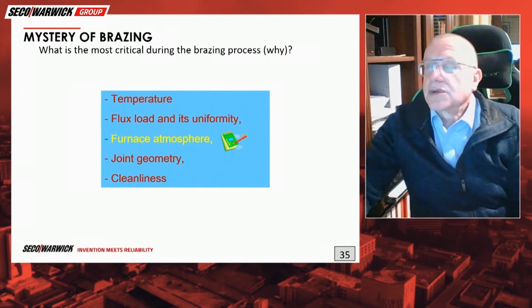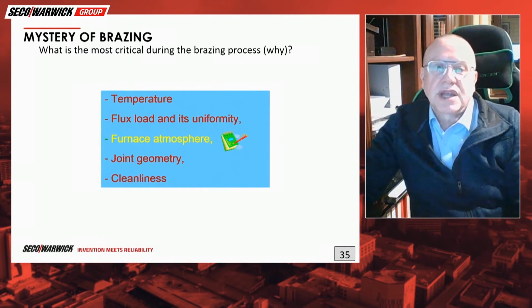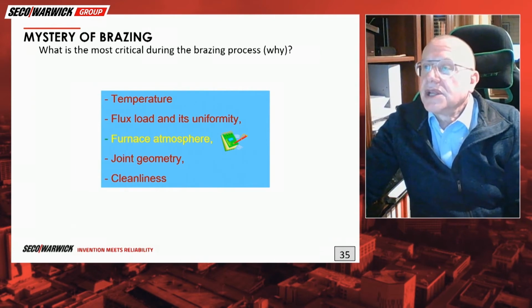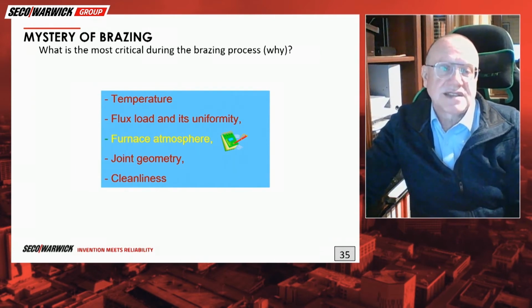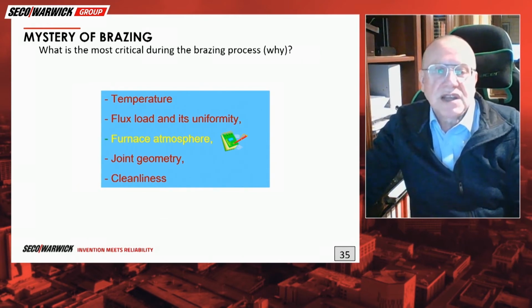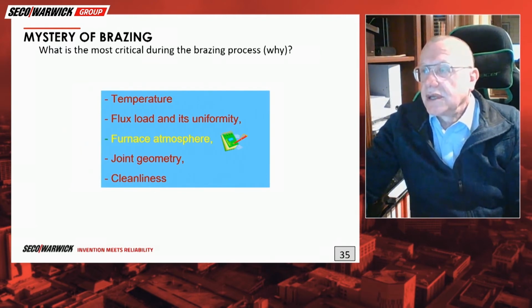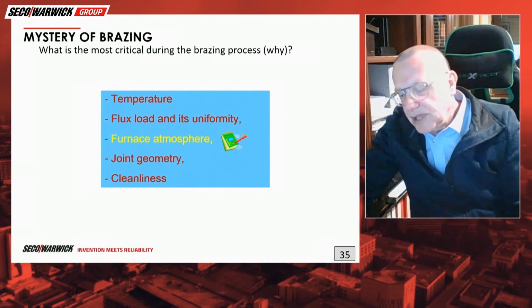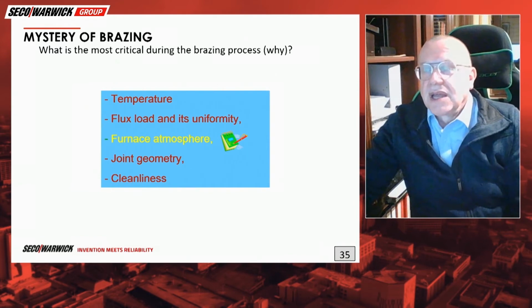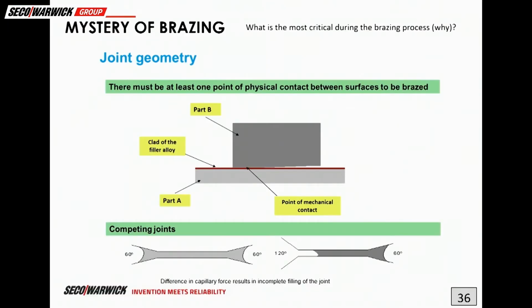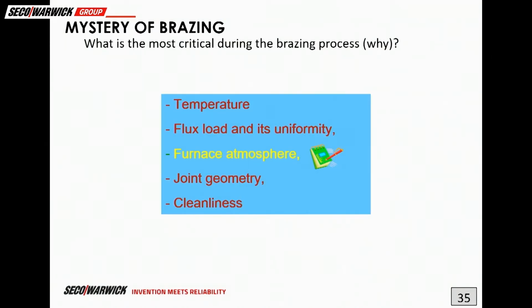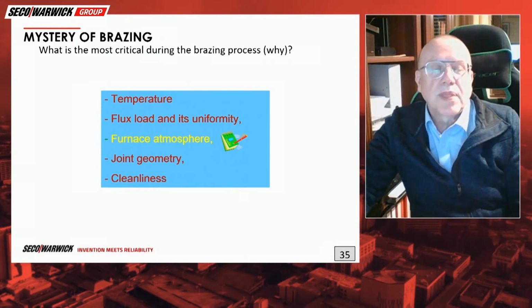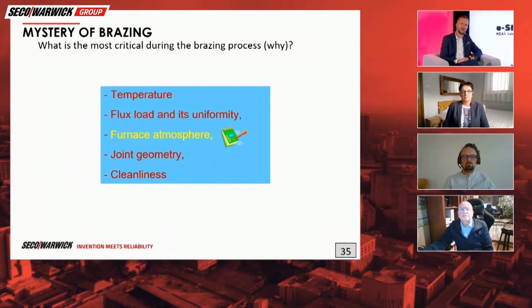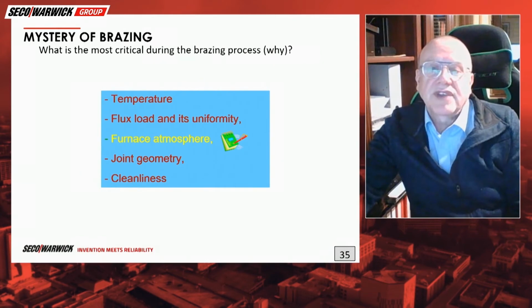And the next point is flux load and its uniformity. Flux, as I mentioned at the beginning of my speech, is needed for cleaning the surface. Every metal surface is coated with oxide, and that oxide must be removed in order to create the metallurgical bond between the filler alloy and the base metal. Fluxing is actually a separate field, and it's a very important process. But one thing is key: flux should be distributed on the surface uniformly and with the required load. According to flux, do I have a correct understanding that it's mostly reserved for aluminium brazing? Yes, but also for copper brazing you need flux, right? Yes.